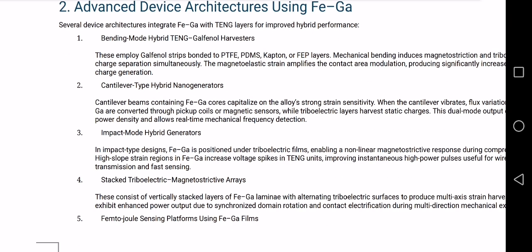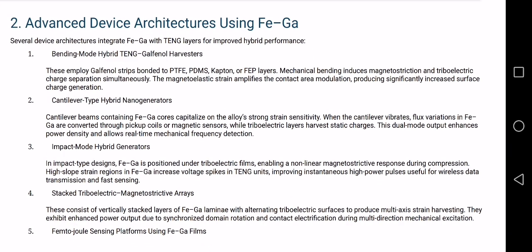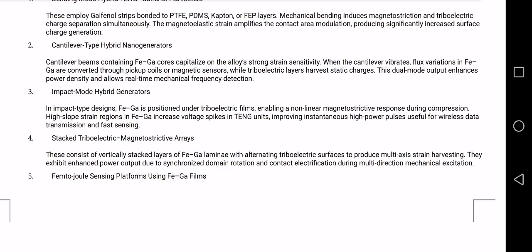Okay. Second is cantilever type hybrid nanogenerators. In this design, FeGa is placed inside a cantilever beam. When the cantilever vibrates, FeGa produces magnetic flux changes. Coils or magnetic sensors detect this flux. Triboelectric layers generate surface charge, and its benefits are dual mode energy output, real-time frequency detection, and high sensitivity to small vibration.